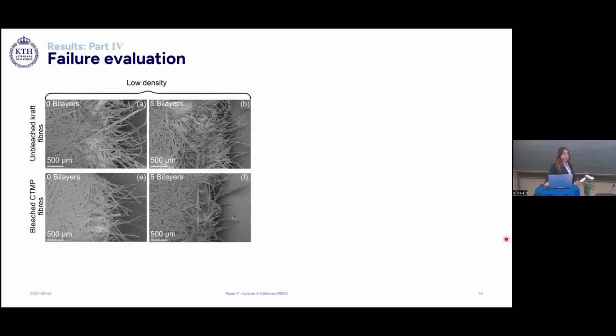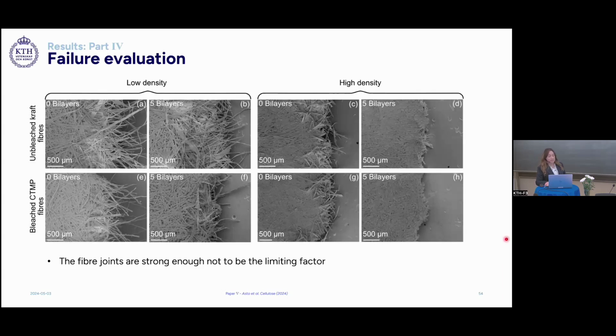To evaluate the failure mechanism of the paper sheets, the samples were imaged with the SEM after the tensile measurements. And looking at the SEM of the papers at low density, we see that we have a lot of fibrillation and fiber pullout for both the untreated and the treated papers. At high density, we can see that we have much less fibrillation of the high density sheets with no bilayers. And with 5 bilayers, we can see that we have almost no fibrillation, and the crack is clean and straight in the thickness direction, which means that the fiber joints are strong enough not to be the limiting factor.